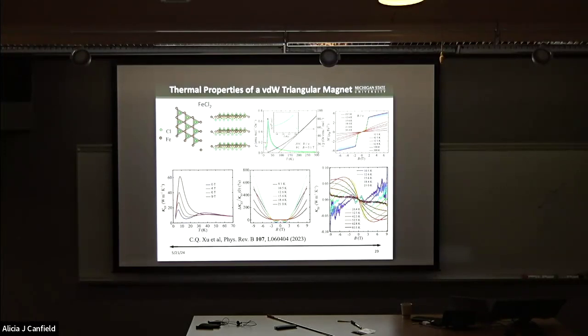we are going to see a metamagnetic phase transition. Interestingly, when we did the thermal transport studies, we found that the system shows a very large magnetothermal conductivity. You can see that at 9 Tesla, the magnetothermal conductivity reaches almost 700%. It's very, very large.